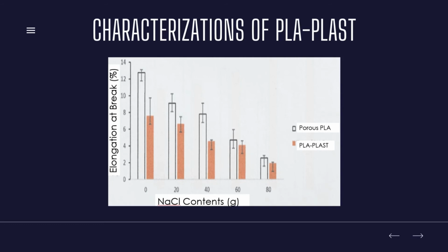Second, the effect of NaCl content on elongation at break of porous PLA and PLA plus. The trend of elongation at break decreased with the increasing of NaCl content for both porous and PLA plus. It was found that the porous greatly produced through leaching process of NaCl content. The elongation break of PLA plus are lower than the porous PLA due to high surface force energy, which make it elongate and fracture faster. Thus, increasing the amount of porous, the higher the surface force energy.